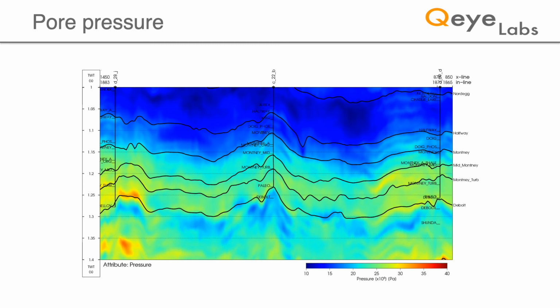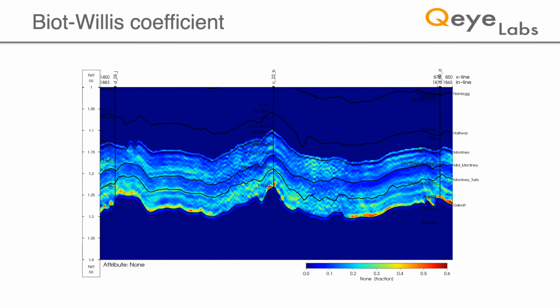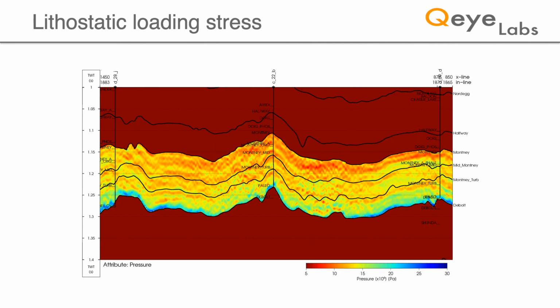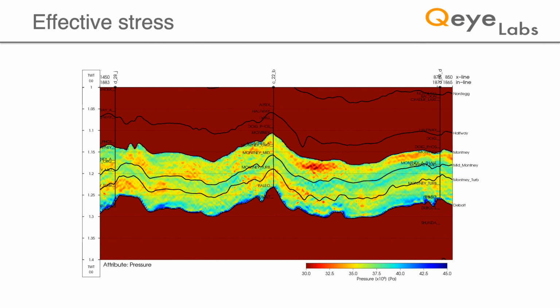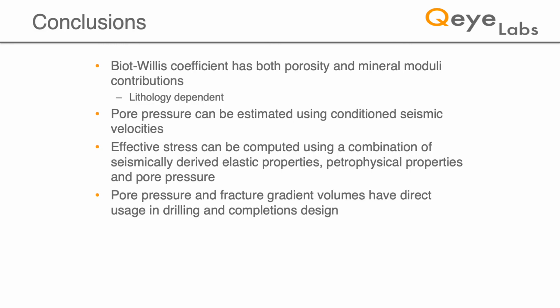So here's the final result of the pore pressure, the Biot-Willis coefficient from the inversion, and the lithostatic loading stress from integrating the density. And here is the effective stress by combining all those components in that minimum closure stress equation. So in conclusion, the Biot-Willis coefficient has both porosity and mineral moduli contributions and is lithologically dependent.